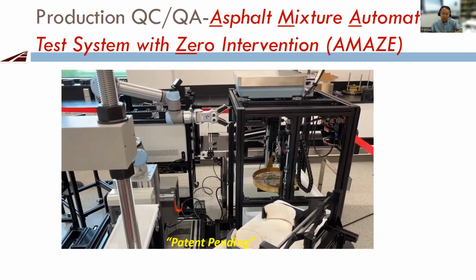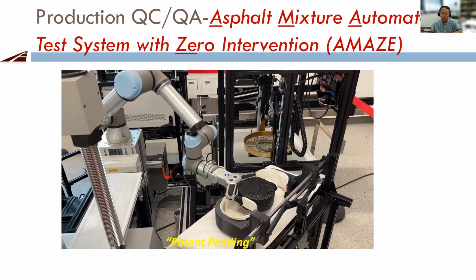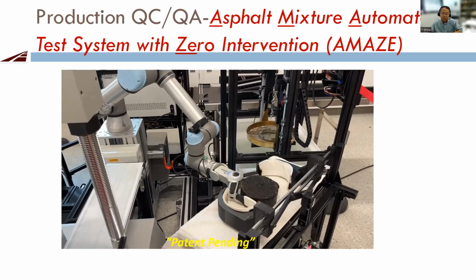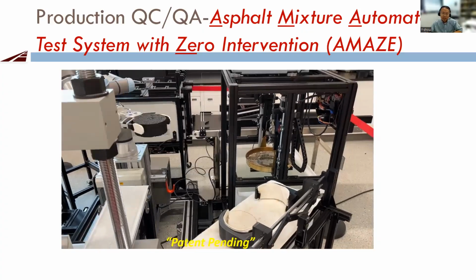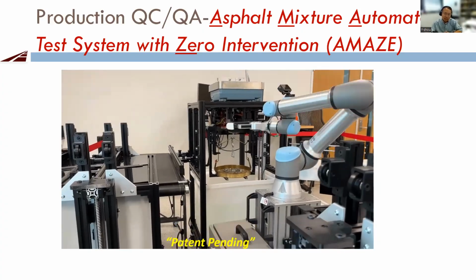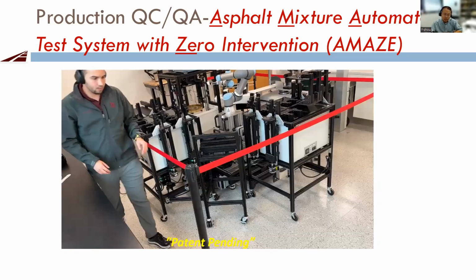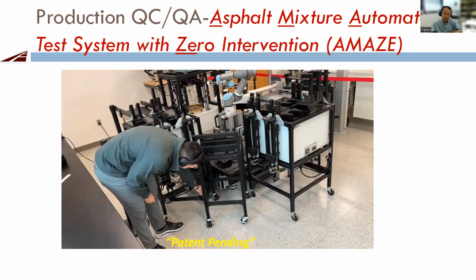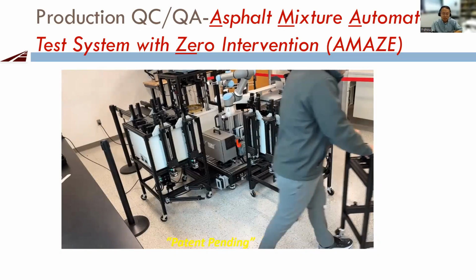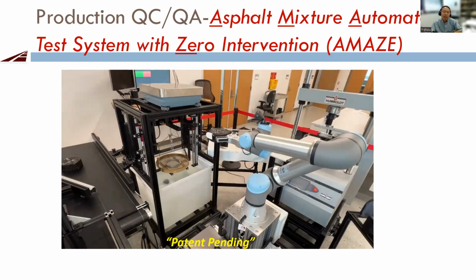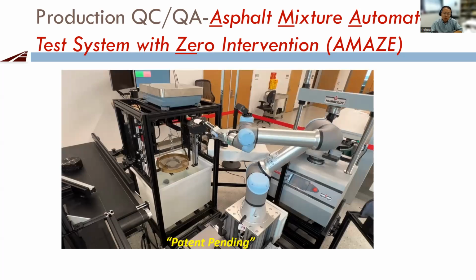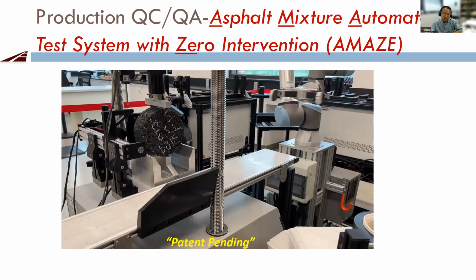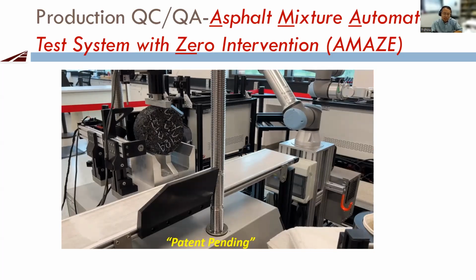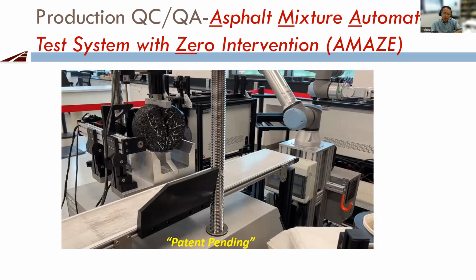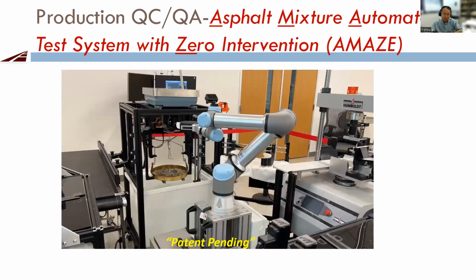The next thing we're going to do is the SSD drying of the specimens. After this SSD drying, we get another weight, the SSD weight, and then we put the sample on this little carrier. If you don't want to do any further tests, you can take your sample away. So that finishes that test, and we get another specimen. This one is going to run the IDEAL-CT test, or IDT indirect tensile strength test. You can see the loading frame crushing this specimen. And then we move the specimen out of this loading frame and into the trash can.